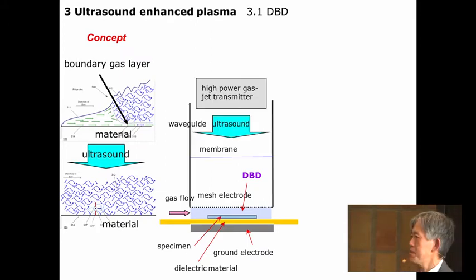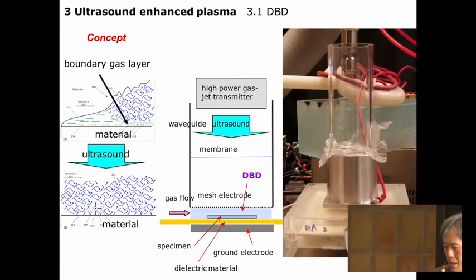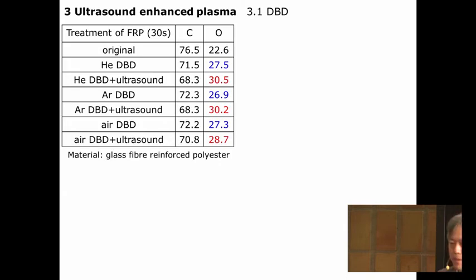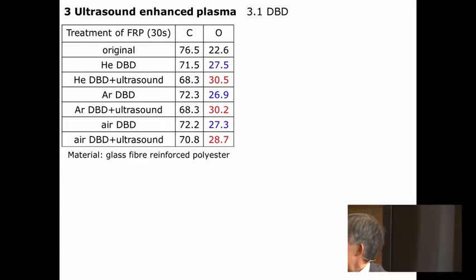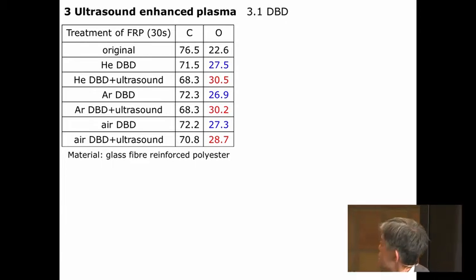And then this very simple setup was designed with the DBD concept, but we have a mesh electrode so that acoustic energy can pass to the surface directly. So this is the first generation device. And then this is the result of the treating, again, blade material, polyester with glass fiber. And then I measured the oxygen content. Consistently, you can see the blue one with the red one.